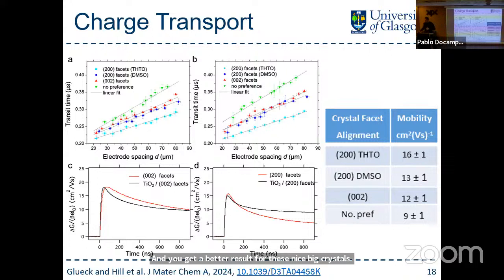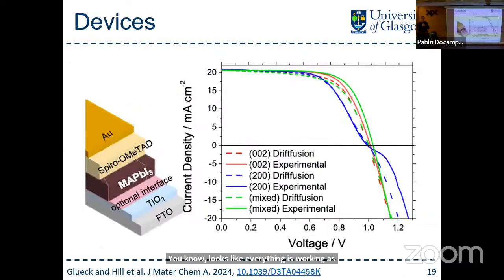Looks like everything is working as expected, and then we made a device. And the one you would expect to be the best, the one with the biggest crystals and the least amount of disorder, is the worst material. Well, what have we done wrong? We've minimized the ion defects. We've done everything right, and yet our device is not right. It's actually the worst one of the lot. When you start looking into this, when you get this kind of S shape, that normally indicates you've got some kind of energy barrier at one of your collection interfaces, so one of your contacts is not working great.